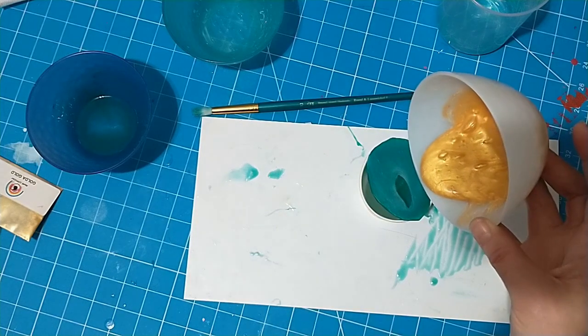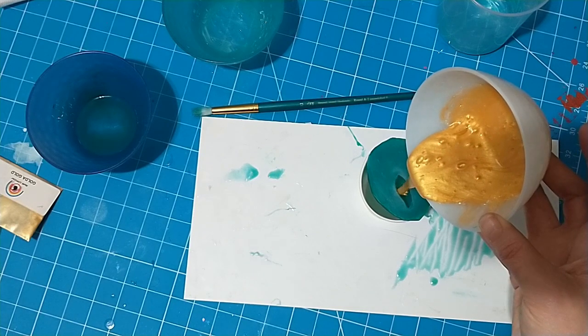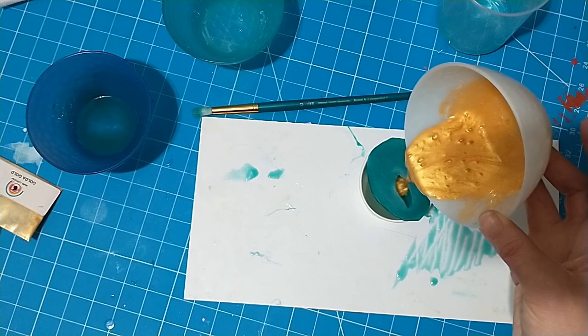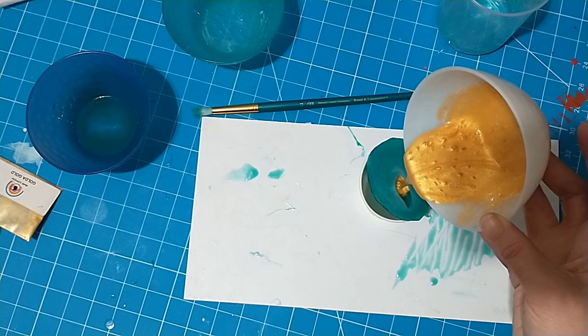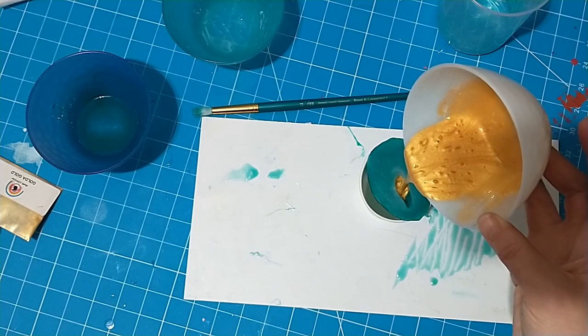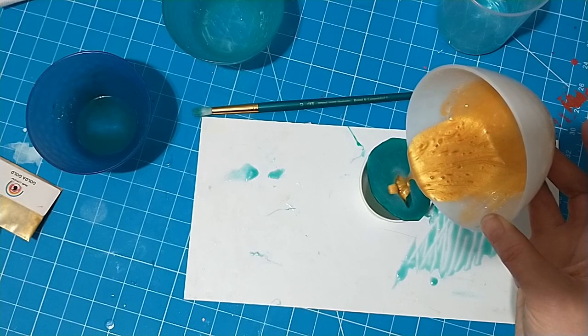I'm going to try and pour it in a very thin stream to help it go down in there and fill all the cracks and crannies and not have any little bubble voids form. Because the molds sometimes have little narrow areas, particularly the tips of the leaves on this are going to want to hang on to bubbles. Anything that's narrow, has a point on it, the small area is just going to want to have bubbles, so you pour it in slowly so it oozes down into those areas. As I pour it in a big gloop, it's going to fill up the top and trap bubbles down at the bottom, right? Also, pouring in slowly when you use a mica pigment can leave the end result looking pretty cool, because all those little bits will form ripple patterns down in there.